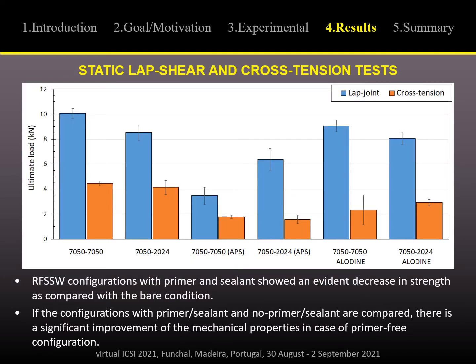The test results are presented here in graphical form. It's evident that configurations with primer and sealant showed an evident decrease in strength as compared to the bare condition samples. And if we compare the configurations with primer and sealant with the no-primer test batches, we can see a significant improvement of mechanical properties in the case of the primer-free configuration.